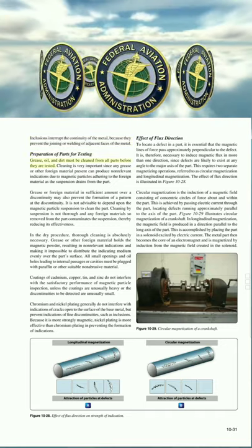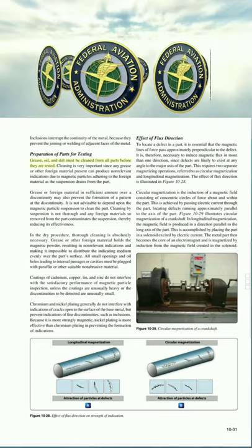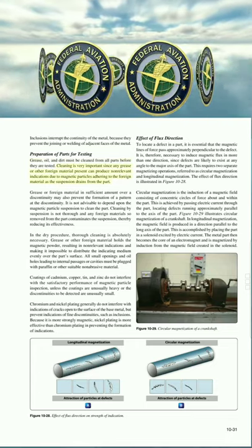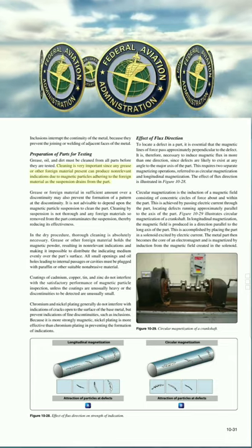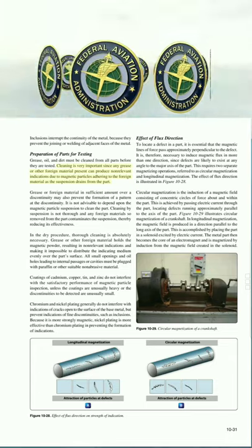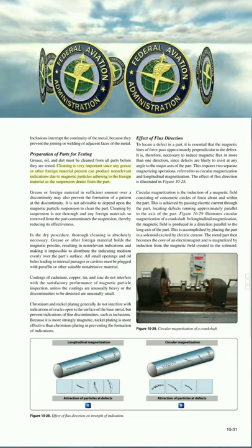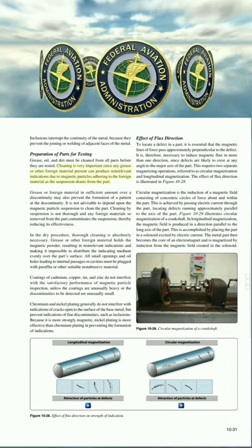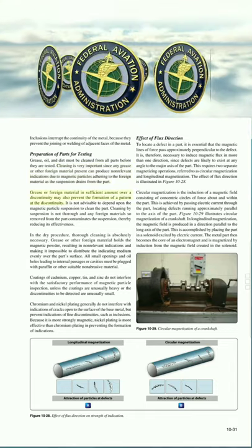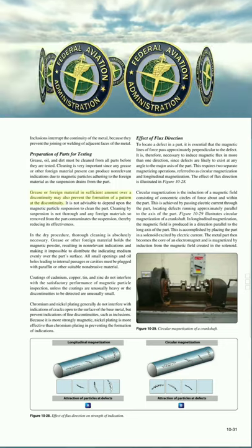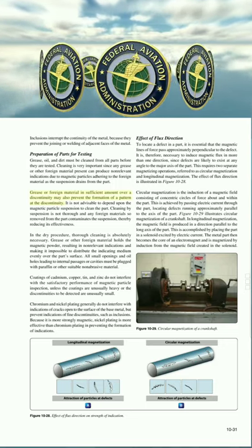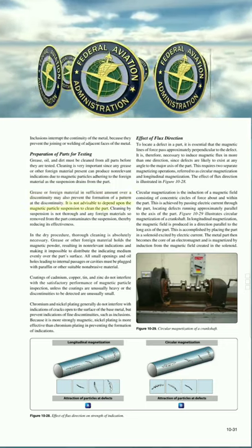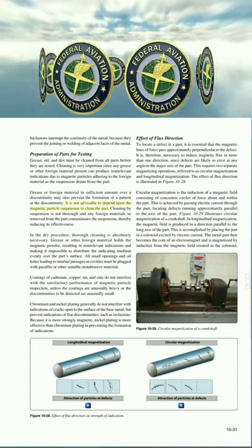Grease, oil, and dirt must be cleaned from all parts before they are tested. Cleaning is very important, since any grease or other foreign material present can produce non-relevant indications due to magnetic particles adhering to the foreign material as the suspension drains from the part. Grease or foreign material in sufficient amount over a discontinuity may also prevent the formation of a pattern at the discontinuity. It is not advisable to depend upon the magnetic particle suspension to clean the part.